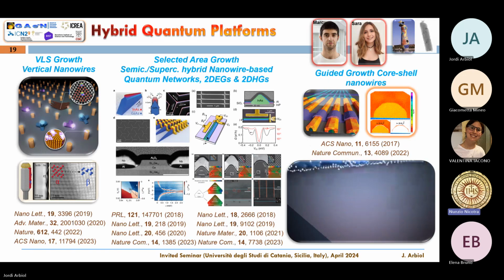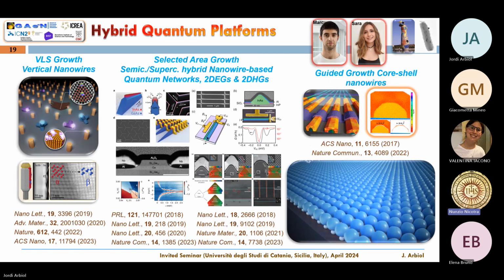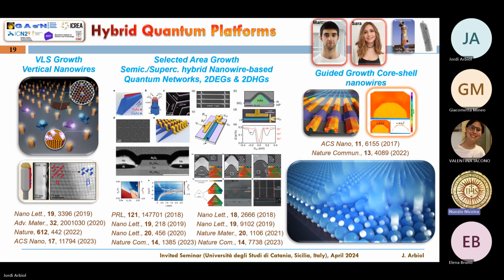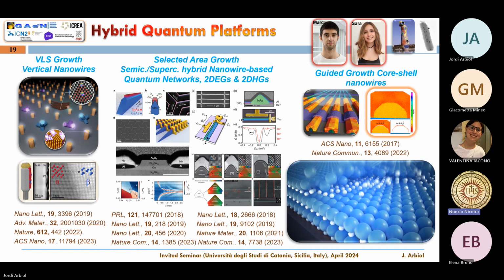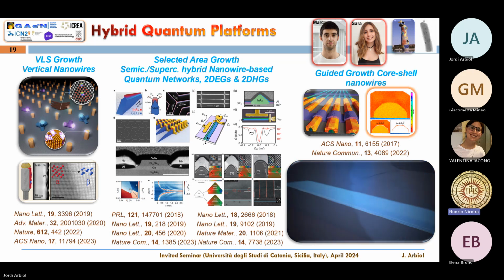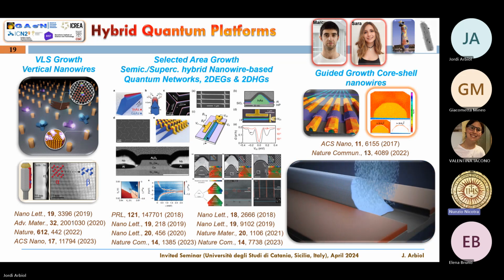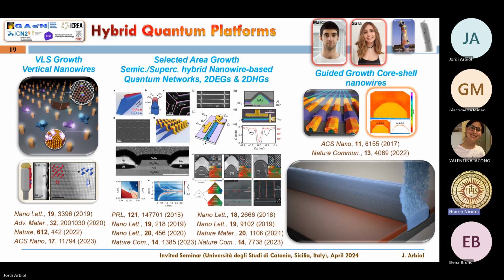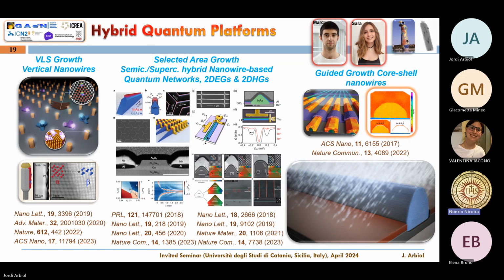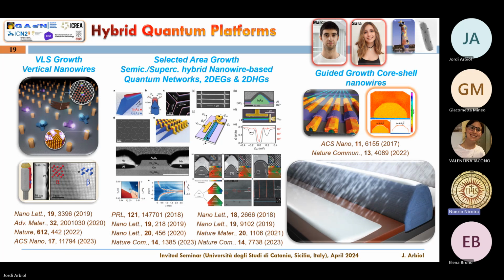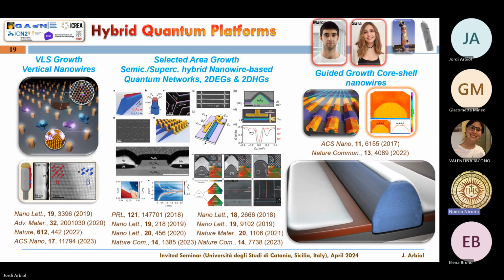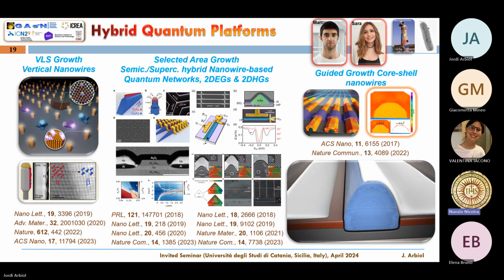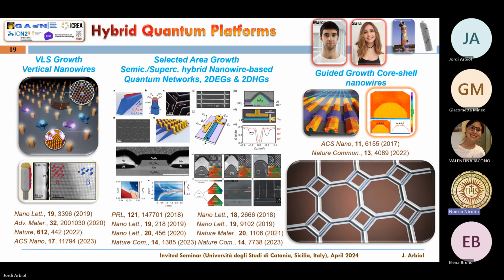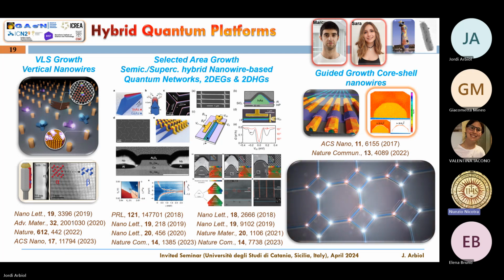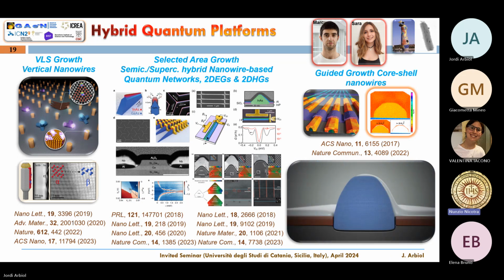So let's see. In all this, we have been working a lot with these different types of materials. And at the end, what I told you is this selected area growth, in which you prepare some trenches on top of the substrate, and you only grow the material inside the trench. So this is the semiconductor. And once the semiconductor is grown, you can couple it with the superconductor only on one or two of the facets. Like here, this can be aluminum, for example. You can use aluminum as superconductor. And then here you finally have the Majorana network with a lot of interconnected quantum bits.